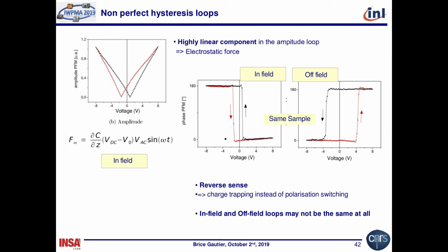It's not the same sign. Compare. It's like a mirror, and the hysteresis loop is in the wrong sense. It's not correct. Compared to off-field, the hysteresis loop is completely correct. Here you have a problem with charge trapping. What you see is not piezoelectricity, it's charge trapping and detrapping, and trapping and detrapping.